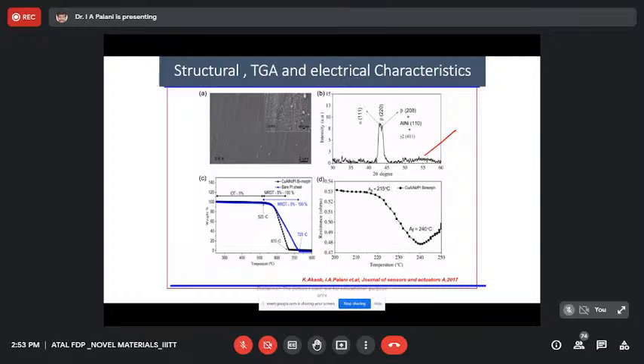And this is a DSC analysis which we have done. This DSC analysis gives us clarity about the austenite start and the austenite finish of the shape memory alloy structure. Generalized DSC of a shape memory alloy structure will have something like this: an austenite start, austenite finish, martensite start, and martensite finish. This characterization will help us narrow down the window at which you can use this material for a particular application.